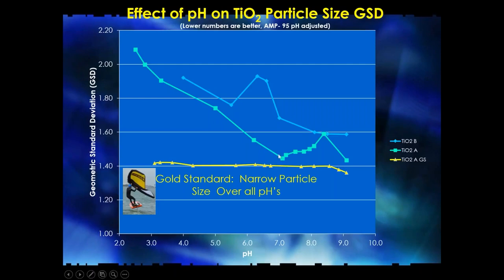Now, this translates to a 10% reduction in the amount of TiO2 that you need for high hiding power. And so we would say, okay, here's two commercial grades. If we happen to be making paint at 8.5, they would look the same. So it didn't matter whether you went to A or B, you're living in the world of the blind, and the one-eyed king reigns, and so nobody knows any different. This is the best right here. But it changes according to pH, and you have control over that with the particle size analyzer.